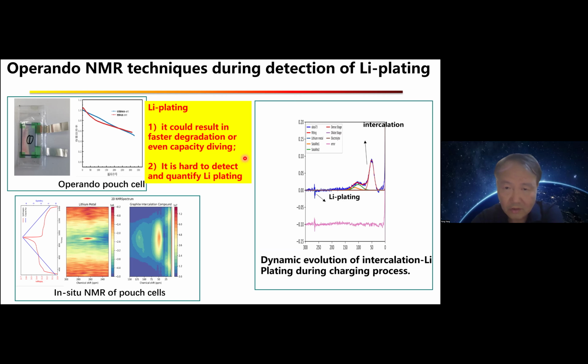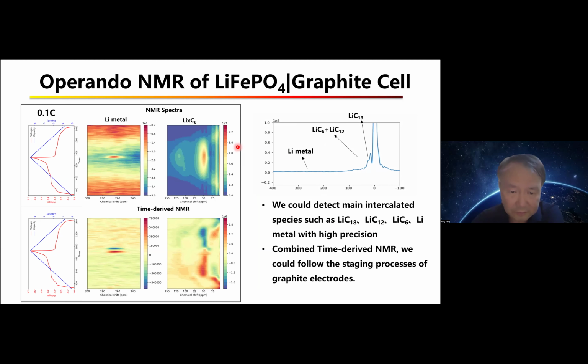And also if you check the time-dependent evolution of the different lithiated graphite, you can also see the evolution and formation of the lithium plating. We can use this kind of differentiated signal to follow the staging process of graphite and also some formation of lithium dendrite and dissolution of the dendrite. That's very convenient, combining this time-derived NMR.